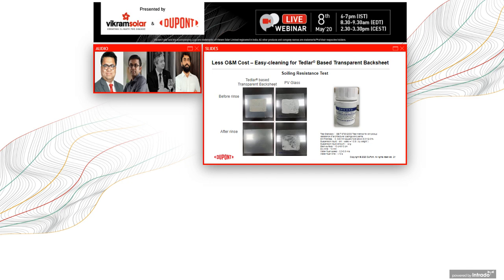Ivan also mentioned the lower O&M cost and I'm showing some actual results here. This is actually, again, a standard China standard test for soiling resistance. What we see here is a comparison between a transparent Tedlar backsheet module on the left and glass on the other. And before rinse, we see all the soiling over here on the top. And after a rinse, which is part of the standard test, you can clearly see the difference between the transparent backsheet versus solar glass, which is used here.